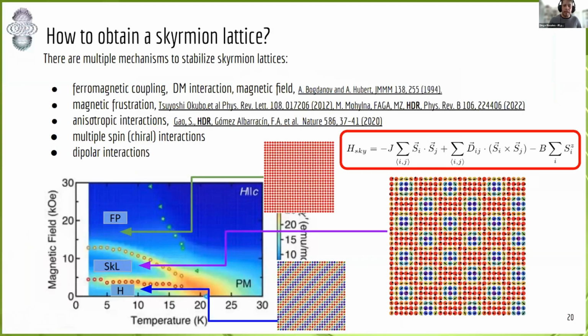Again, there are multiple mechanisms to stabilize a skyrmion lattice. The simplest way to get this configuration is by the competition between ferromagnetic coupling and Dzyaloshinskii-Moriya interaction plus the Zeeman term. This is the typical Hamiltonian for this situation, where we have an exchange coupling between magnetic moments. This is the Dzyaloshinskii-Moriya interaction along the perpendicular or along the plane, the layer, and this is a Zeeman term.